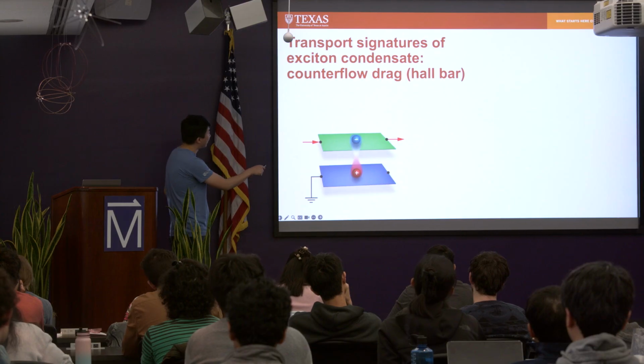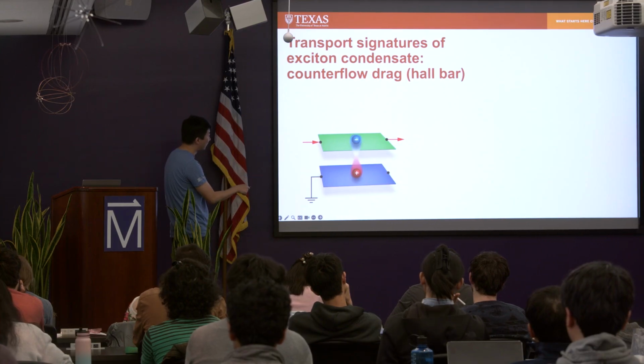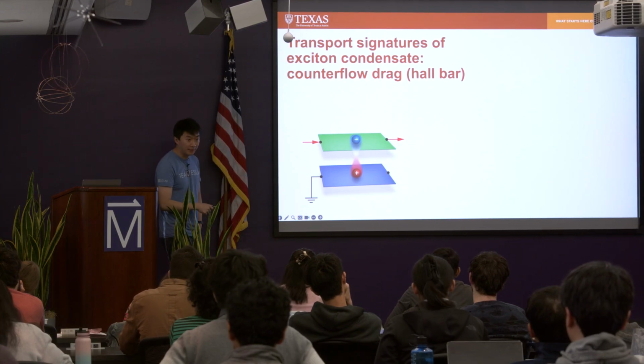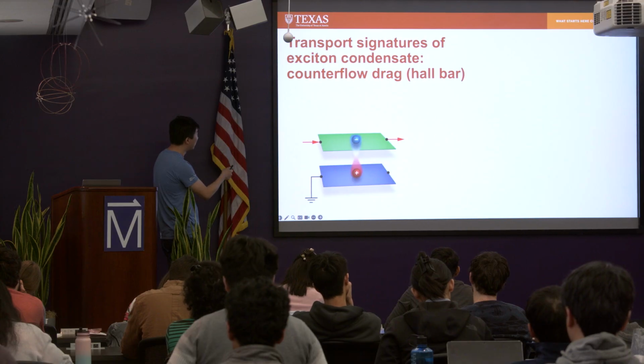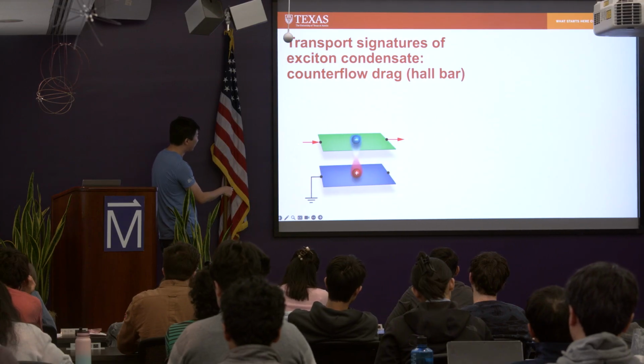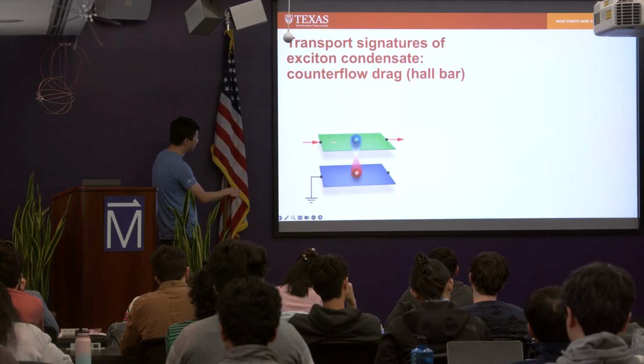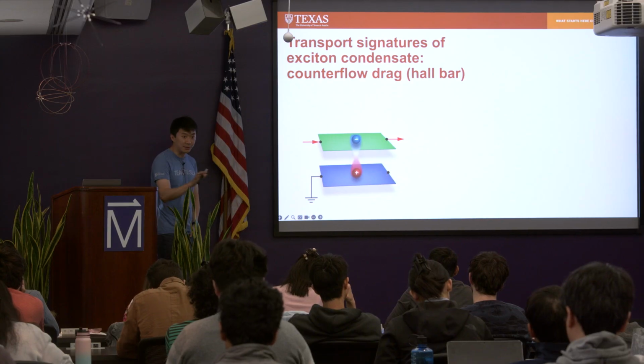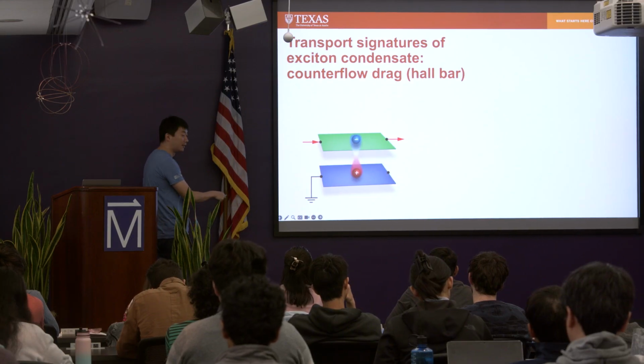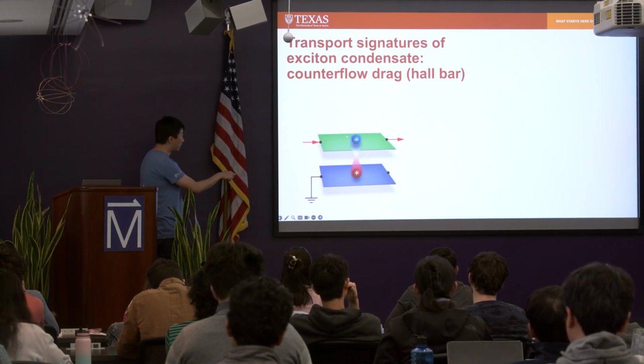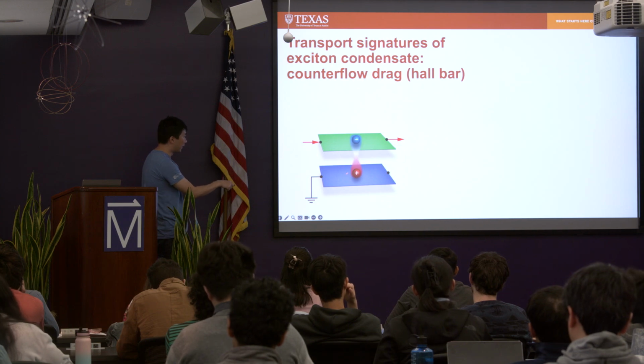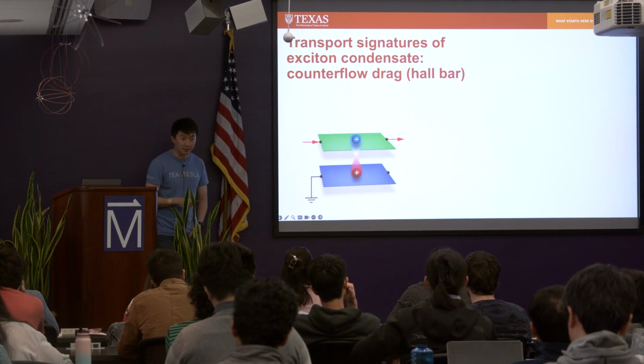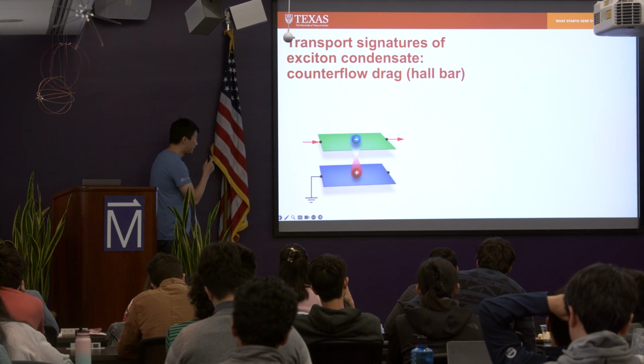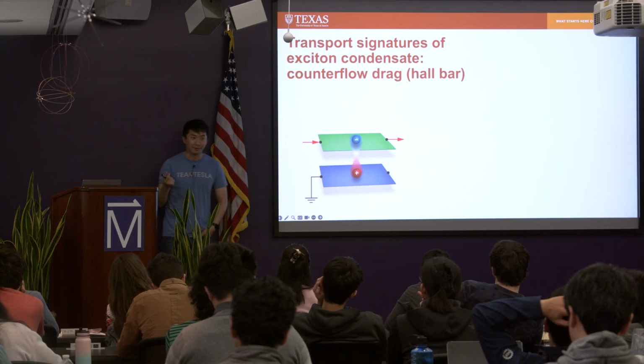So if you take the double Hall bar sample geometry, where each layer is a square, right? One type of measurement you can do is called counterflow drag, where you flow current from the top layer, left to right, and the bottom layer is passive. There's no active current flow, you just ground it, right? And then you can measure the transverse resistance across both layers and also longitudinal resistance across both layers, right? So this can probe one very unique feature.